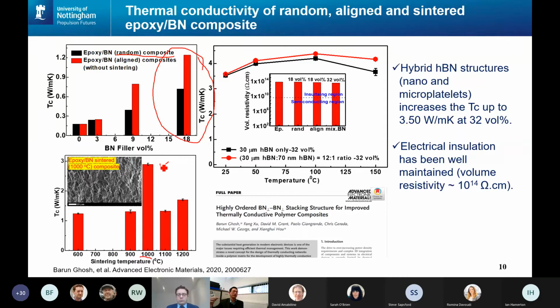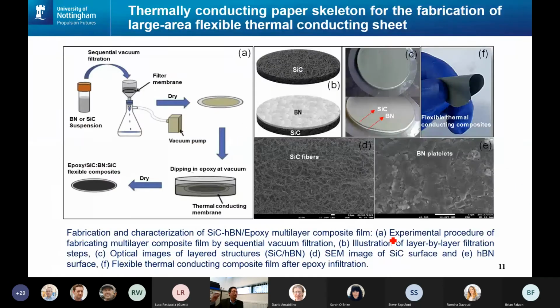In order to promote the sintering, another method is that we can try to add some nanoparticles. These nanoparticles will stay at the interface of the big boron nitride platelets. Then during the sintering, the nanoparticles can help the diffusion bonding between the two platelets. Finally, we can get a value of 3.5 watts per meter Kelvin at 32% volume fraction. For electrical insulation, we can keep the volume resistivity slightly higher than 10 to the power 14 ohm centimeter. We have one publication recently here. This method is mainly for bulk materials.